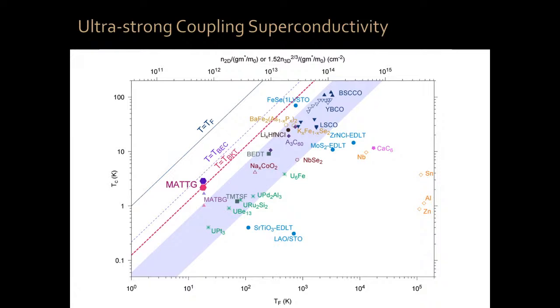So that means that, let's imagine you get a very strong superconductor, like magic angle twisted trilayer graphene. If you were able to maintain that coupling strength, you would be riding as you increase the Fermi temperature along this line, okay? So in order to make a room temperature superconductor, something that will be up there, where the line will be 300, you would need a superconductor which is as strong as magic angle graphene at a Fermi temperature of 10,000 Kelvin, which is smaller than most metals, okay? But you need a much stronger concentration of charge.